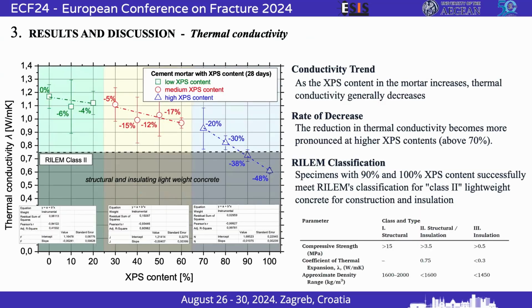Now, moving on to the thermal conductivity, which is a very important property when we're talking about thermal insulation materials, we have seen that it is decreasing. We want the thermal conductivity to decrease. Lower thermal conductivity means that the material can be used as an insulating material. Similar to the compressive strength results, here you can see three different areas: from 0 to 30% substitution, from 30 to 60%, and higher than 70%. What is worth mentioning is that for substitutions of 90 and 100%, the material, according to RILEM, can be classified as class 2, which means that it can be classified as a structural, lightweight, and insulating material.